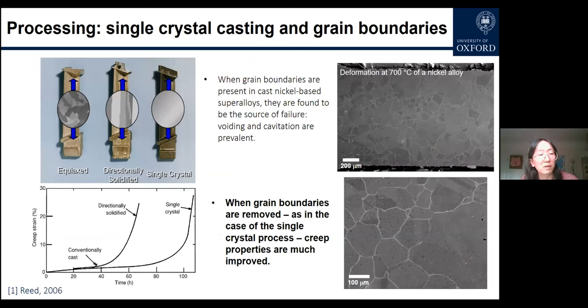One important thing is the creep. As you can see, the equiaxed grains, which come from conventional casting, the directionally solidified material, have aligned grain boundaries, and then there are the grain orientations of 001 or single crystals, where you just remove all the grain boundaries. Therefore, you can test their creep strains. They are quite different as well. The conventional cast material has about 30% of the life of the single crystal in this case, which means the single crystal has really paid off for the creep properties.